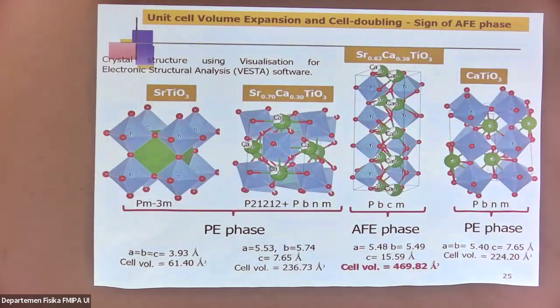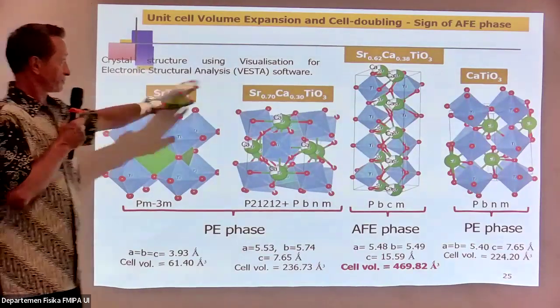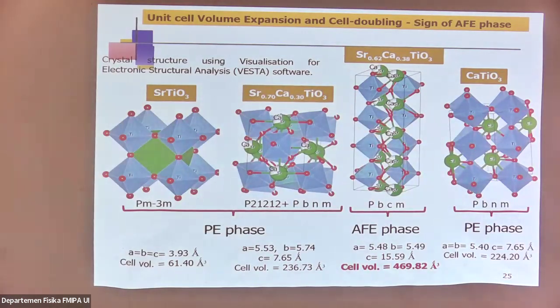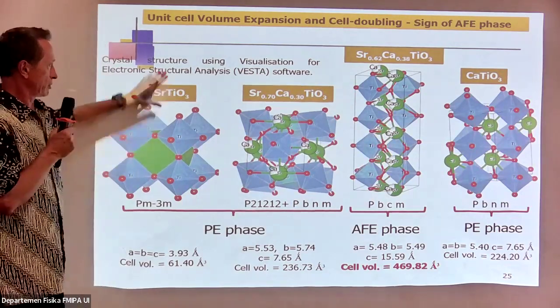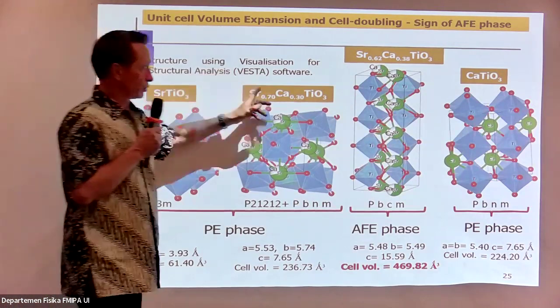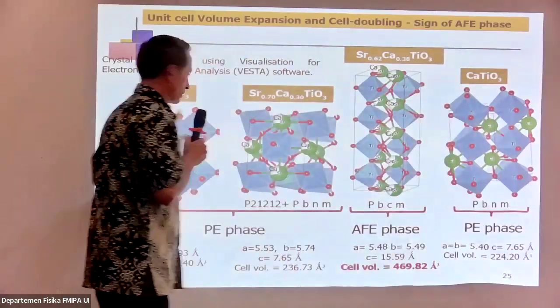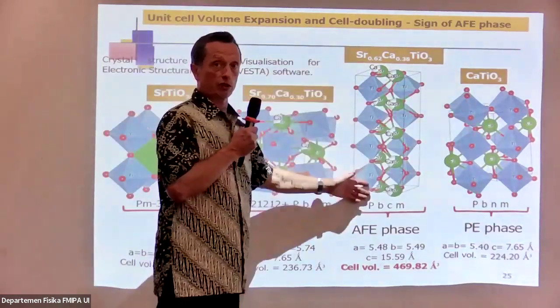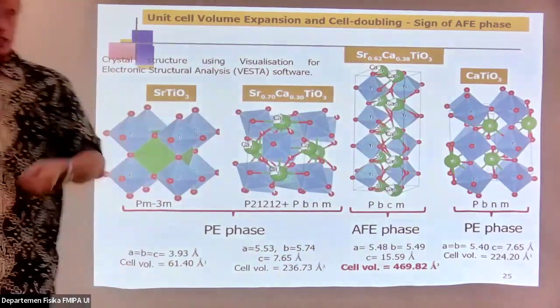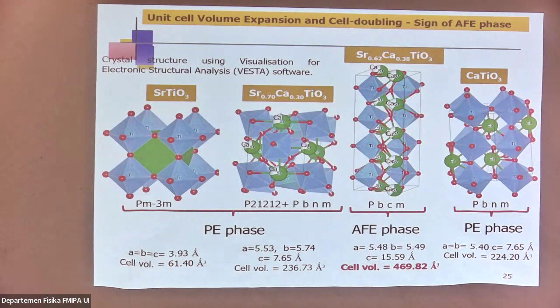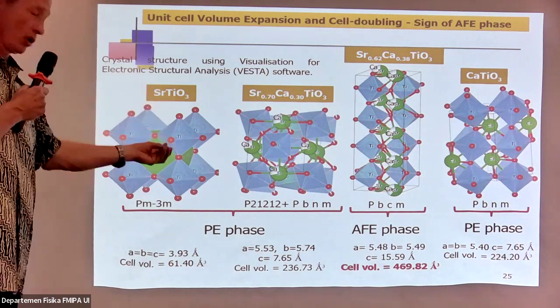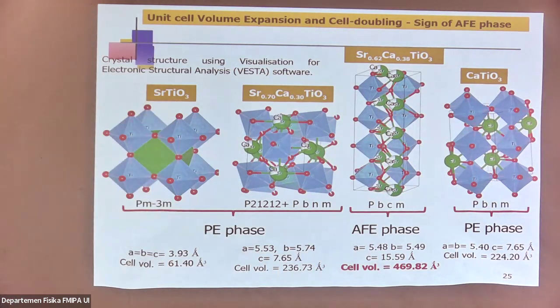And with additional options here, Vesta, it's also possible to visualize finally your structure in function of the doping, because our initial structure was strontium titanate. By exchanging a part of strontium, we included different rates of calcium. So we are between the pure strontium titanate and the pure calcium titanate. And here we revealed theoretically that with a particular percentage, it could be possible to really roughly modify the structure for having finally a possible antiferroelectric phase. And that was revealed only with this theoretical study made by simulation.